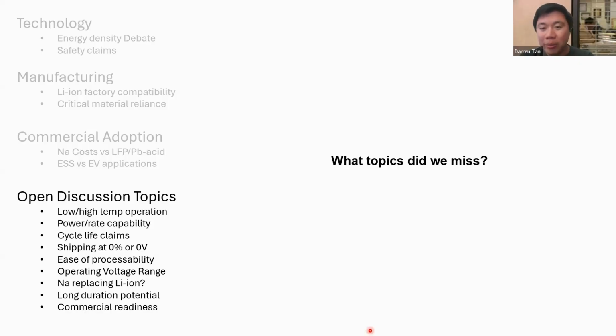Edmund mentioned it's true. Chao Chuan asks, what about operating voltage range? Ooh, this is a long topic. Oh, how do I compress all these ideas? Sodium ion batteries have a notorious reputation for having a wide operating voltage range, right? Your most common sodium ion batteries, layered oxide, operates from 1.5 volts to 4.2 volts. That's more than three times the range, right? And it's a very slopey curve. And some of the others have narrower but still far wider than LFP.